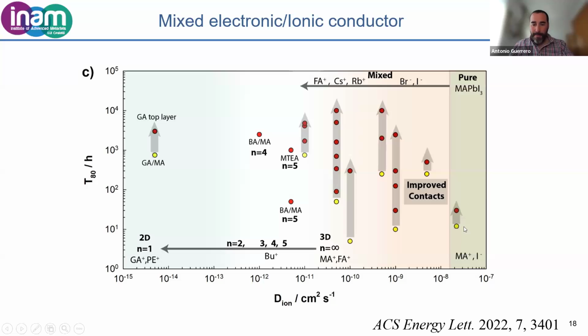So for example, if we use perovskite formulations like pure MAPI, methyl ammonium lead iodide, which has high diffusion coefficients, the ions can move very fast to the contacts. The degradation when we illuminate the devices, as I showed you before, is very fast. And within the first hour, the device has degraded very, very fast. One way to increase the T80 is by reducing the supply of ions that reach the contacts. And this is obtained by, well, these are some values for mixed halide formulations, these yellow circles here.